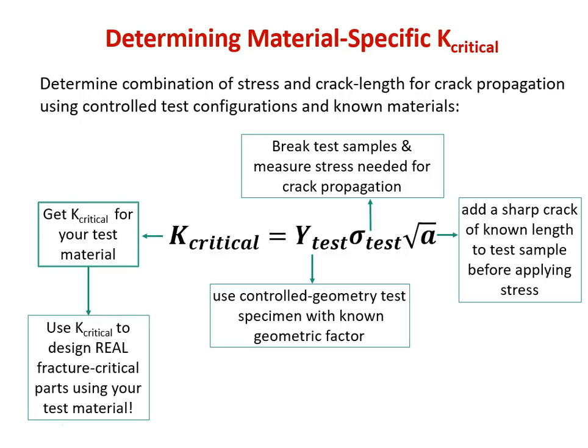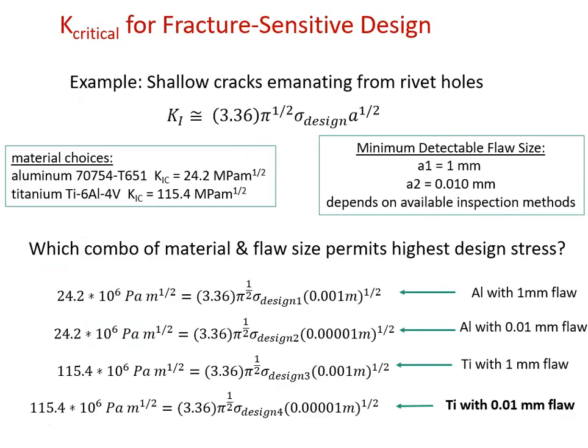You will then add a sharp crack of a known length to the test sample before you ever start applying stress for the test. And in order to add a sharp crack of a known length, you use fatigue, which is actually a failure mechanism, but you apply it in a controlled way so that you know what your starting crack length is. So once you have a set Y test and a set A that you know, you'll load the material up and measure the stress at which it breaks. You'll do that again and again for different crack lengths, and you'll end up with a single K critical, which is then specific to the material. So that is how you get the material-specific component of this fracture scenario.